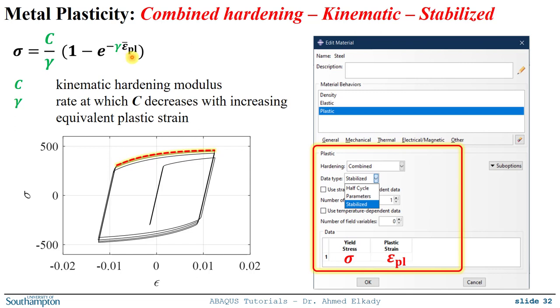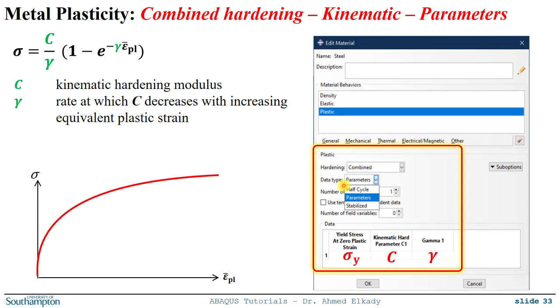We typically use the half cycle, because in most applications we have at least the uniaxial tensile test, but we can also use the parameters directly. So instead of ABAQUS computing C and gamma, we can directly input the values for C and gamma. In an Excel sheet or using a MATLAB code or something like that, you can play with the values of C and gamma in order to generate this relation between the stress and the plastic strain of the plastic branch.